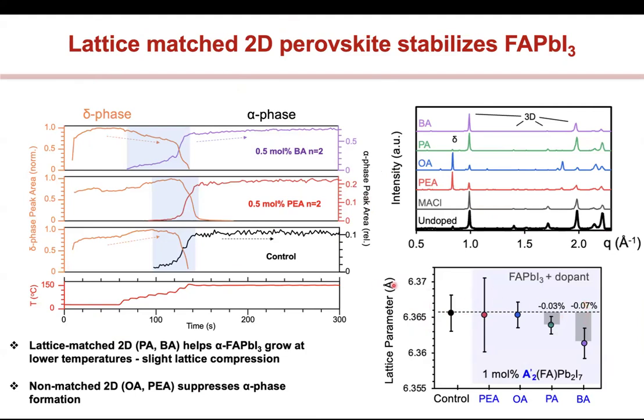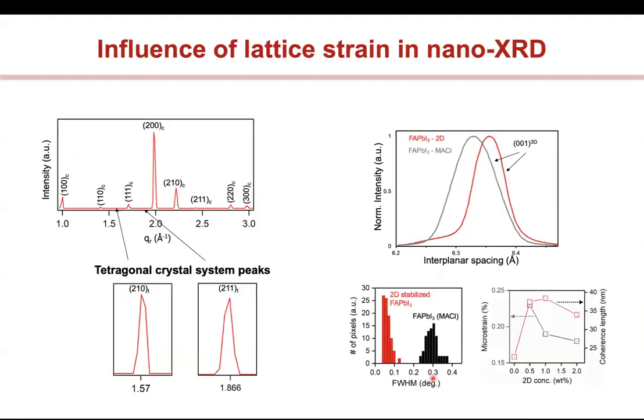But you can see when you add this butyl ammonium, you get this very nice 3D phases of the FAPI, and in fact, the lattice constant of this 3D film matches very well. In fact, it's compressed now, right? And it matches very well to that of your FAPI. So it's actually a compressed film, which is now contributing, it is pushing your tolerance factor down, right? And it's giving you a very stable FAPI phase.